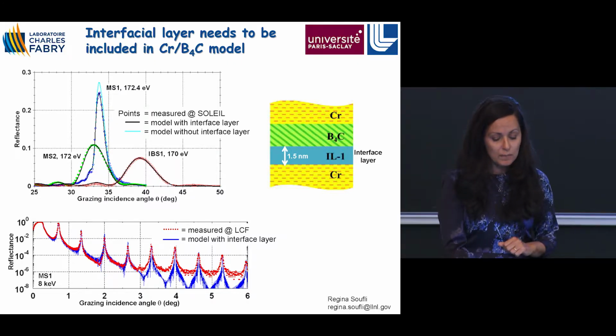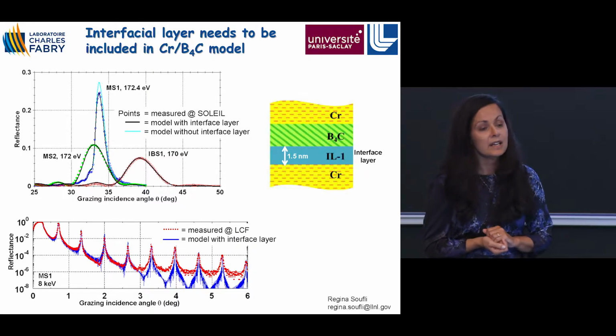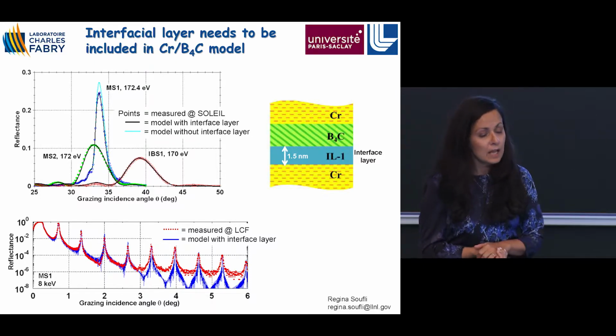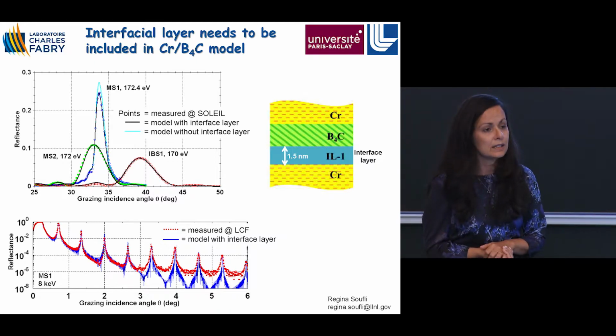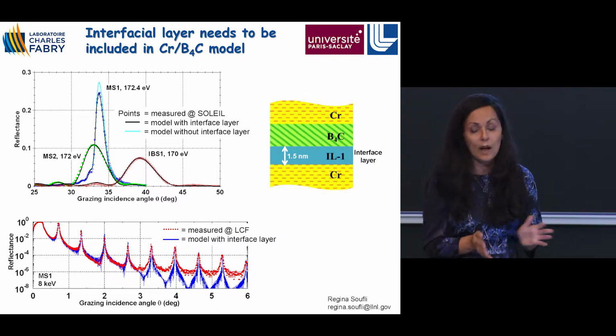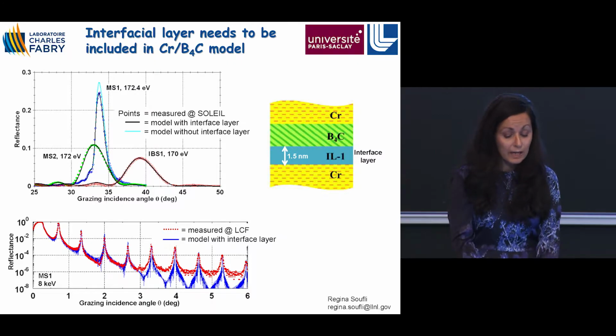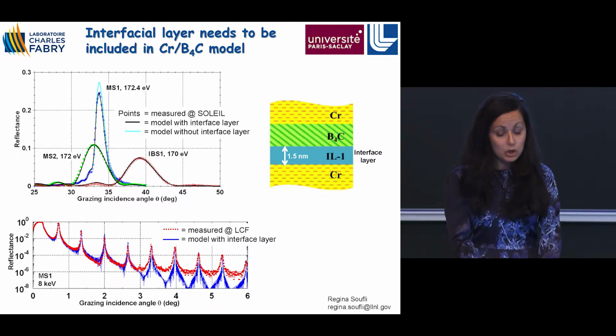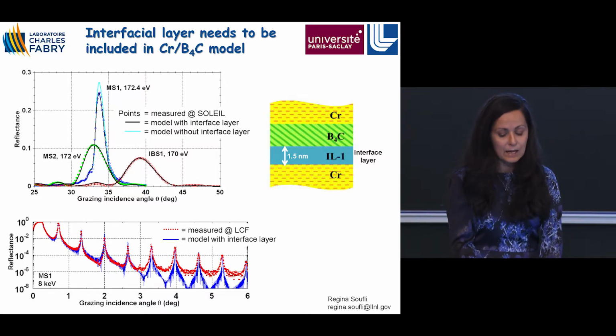Additionally, I wanted to mention about this material system. We measured this reflectivity 3 years after deposition. And the reflectivity was unchanged. So this is a very stable reflective system that can be used in applications that require a long lifetime, and we're very happy with its performance. It also means that this interface layer is very stable over time, and it does not hinder the stability of this coating.